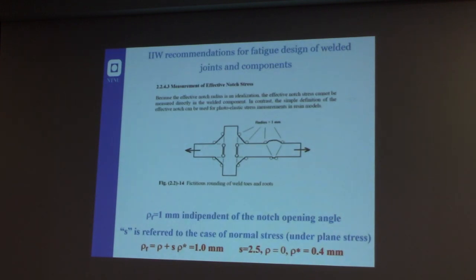This is the only local approach that is accepted nowadays in the standards for welded joints. If you have a welded joint, what you can do is substitute the critical points with the critical radius equal to 1 millimeter, and after that understand where the maximum value of the stress concentration factor is located.